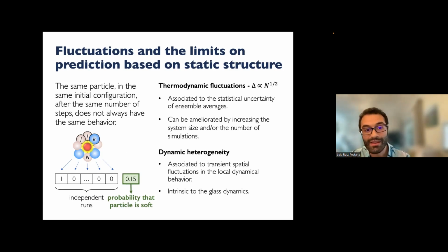Thermodynamic fluctuation is not something that you should be worried about too much, unless you have to make a quantitative prediction under a certain threshold of uncertainty. But thermodynamic fluctuations we can work with. However, in glasses, there is this other thing that is called dynamic heterogeneity, which is associated with transient spatial fluctuations in the local dynamical fluctuations.